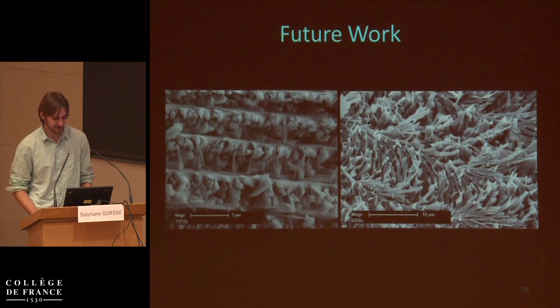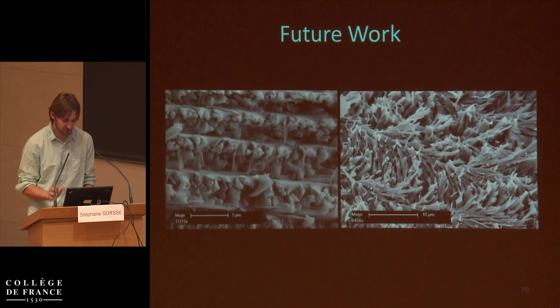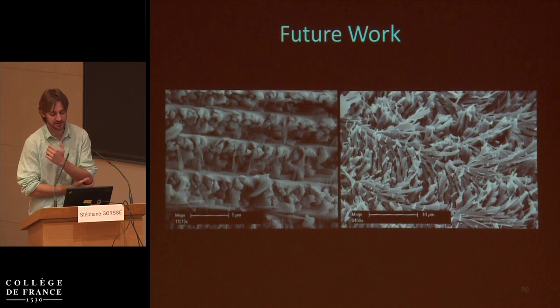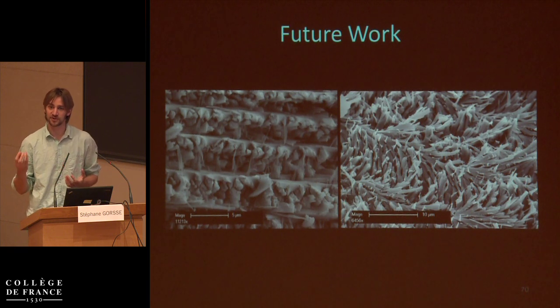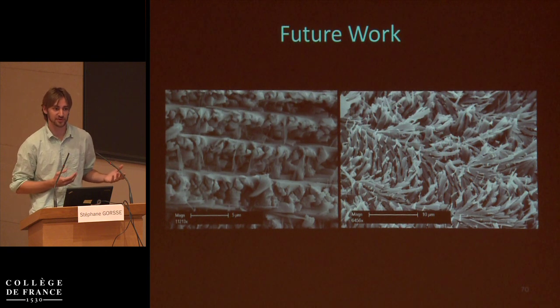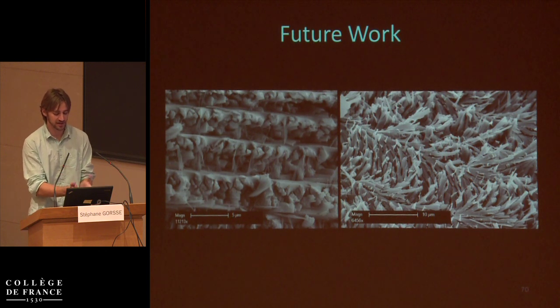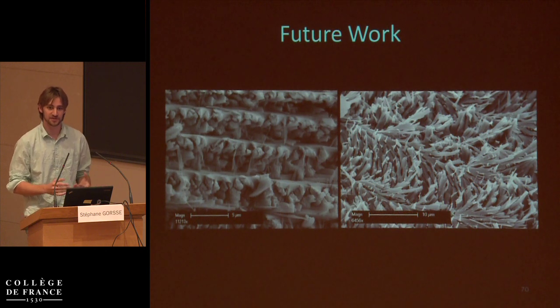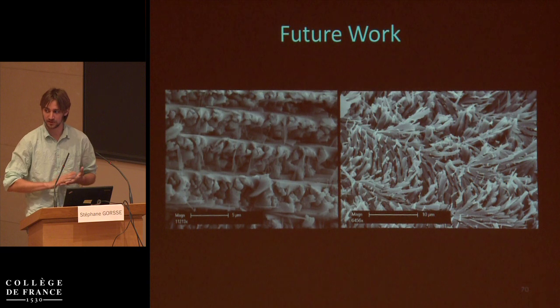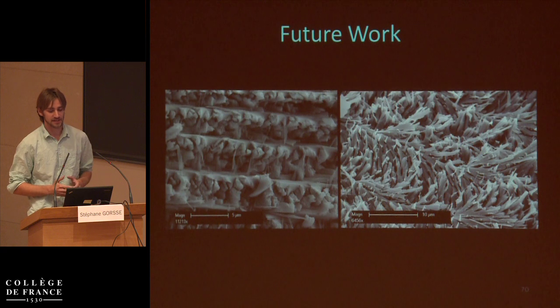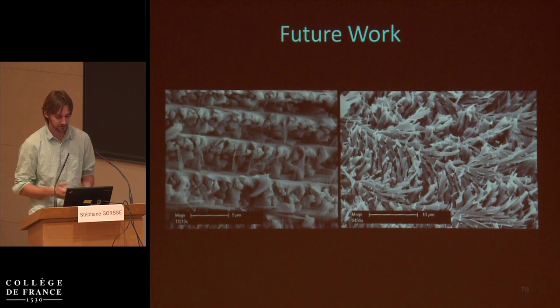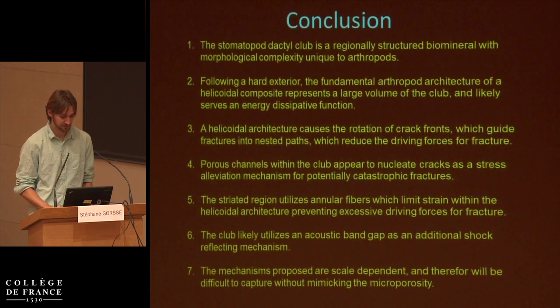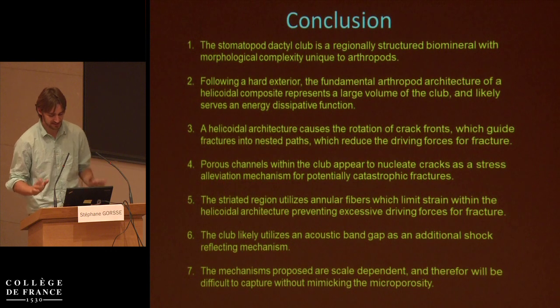And then another interesting thing that I'll end on is that, because this is the structural motif of its entire exoskeleton, the spring that it uses to store all of that elastic potential energy is also using rotated plywood, but you can see that this is a striking difference from what I showed you earlier. And so there's a great deal of parameters within a helicoidal composite, and it appears that these parameters are being tuned for very different functions. If we could further understand this, then potentially we could tune them ourselves and also serve a very large degree of functions. I won't read these, but the last thing I'll say is that